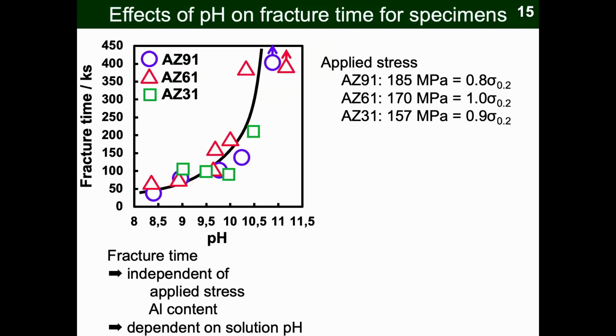So this figure shows fracture time depending on the pH as a function of the aluminum content. This is 91, 61, 31 specimens data. Applied stress is a little bit different. This is my mistake, but when you apply a little bit of change in stress, fracture time is independent of the applied stress, and also independent of the material kind, which is aluminum content in this case, and strongly depends on the solution pH.